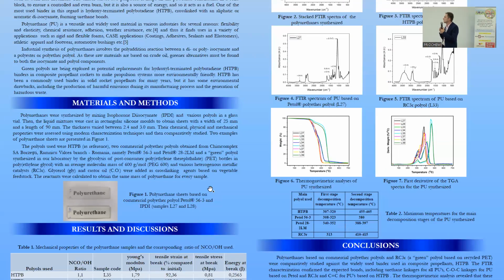The thermogravimetric analysis revealed 2 main decomposition steps that, according to literature, are associated with the breakage of the urethane bonds, the first decomposition step that occurs at a lower temperature, and the second decomposition step, that occurs at a slightly higher temperature, is associated with the destruction of the polymeric backbone.